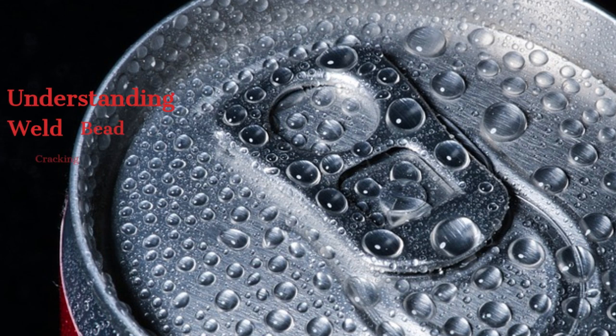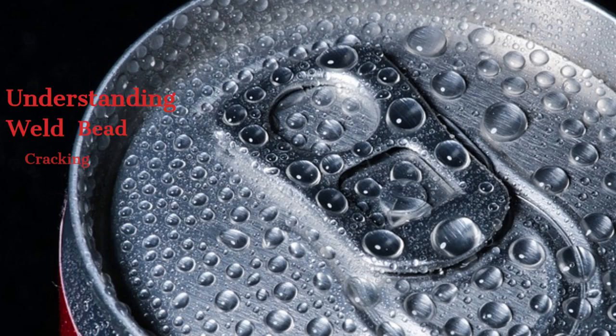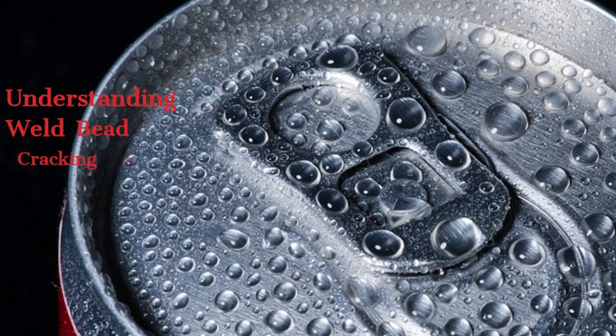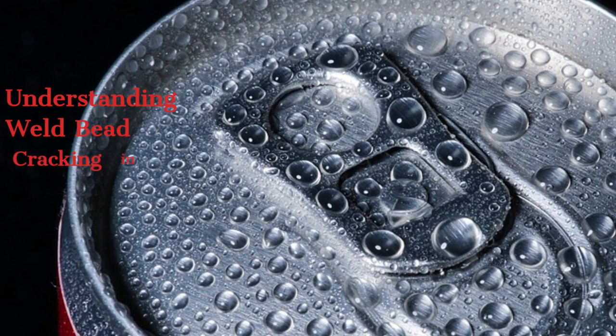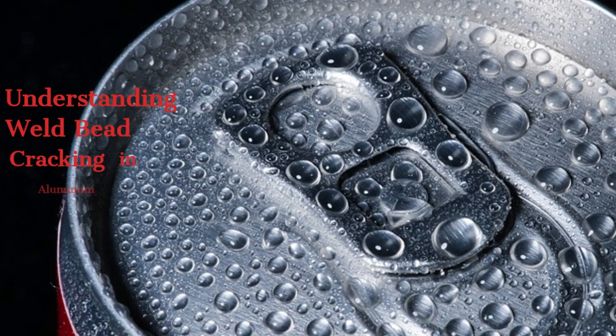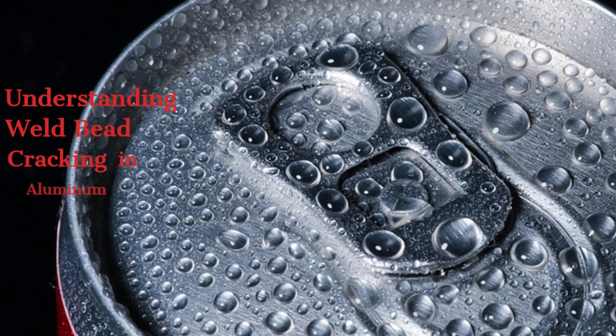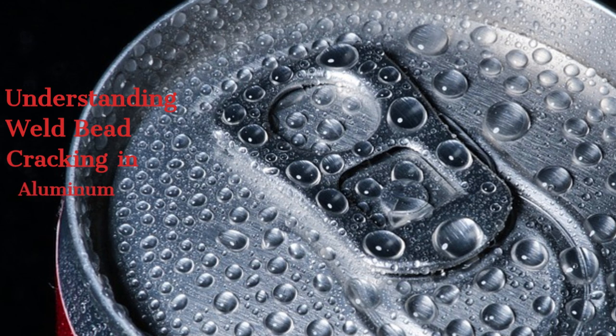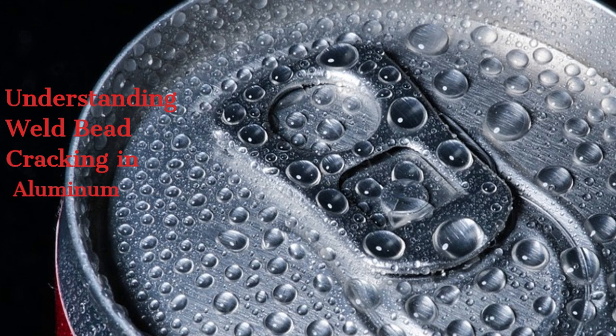Aluminum: light, strong, versatile, and apparently a drama queen when it comes to welding, if not handled well. Its unique properties make it susceptible to cracking. The main culprit, the question most often asked in the exams, is hot cracking or solidification cracking. This happens as the weld cools. Aluminum expands like it's trying to win a hot dog eating contest when heated, and then shrinks back down just as dramatically. This creates stress, especially during solidification, which can lead to cracks. It's like the weld is having an existential crisis.